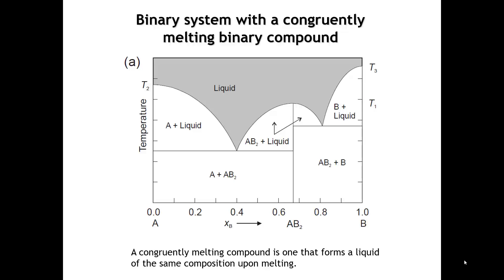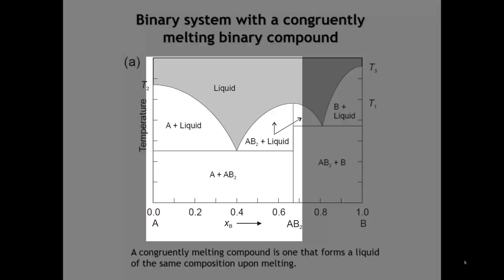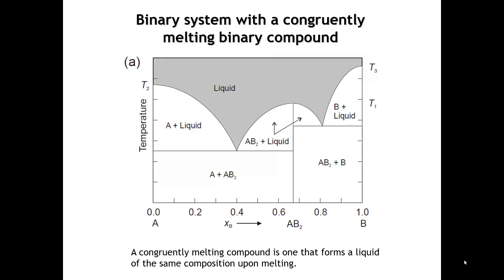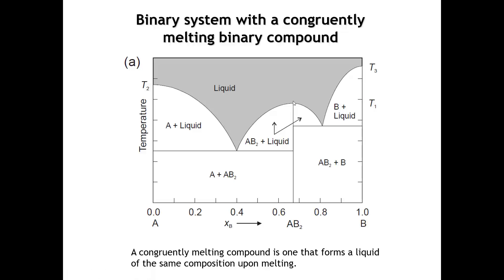The difference being, yesterday one end of the eutectic phase diagram was A and the other end was B. In this phase diagram, let's think about it as a eutectic diagram between phase A and phase AB2, and right next to that we're going to put a binary phase diagram between phase AB2 and phase B. All of the regions shown in white are two-phase regions. Notice that phase AB2 is what we would call a line phase — its stoichiometry must be fixed at that 1-to-2 ratio of A to B. If we follow the vertical line upward, it goes all the way up until we hit the liquidus, meaning compound AB2 is a congruently melting compound. When it melts to form a liquid, the composition of the liquid is the same as the composition of the solid.